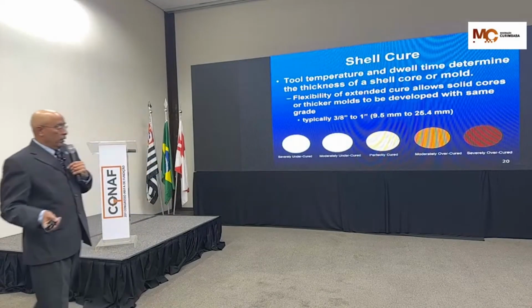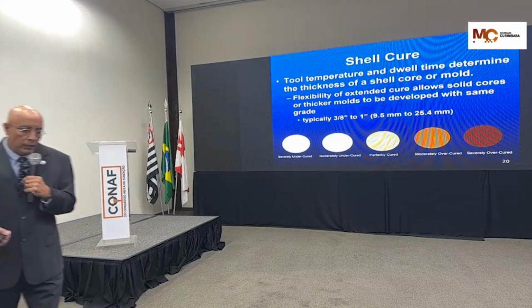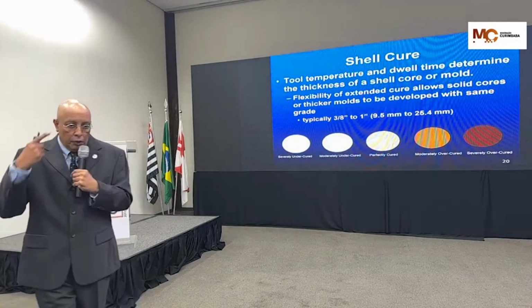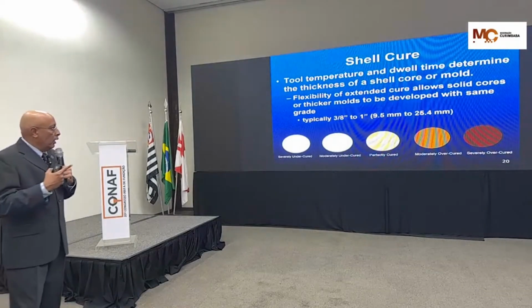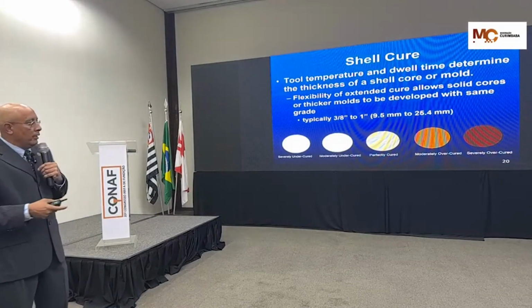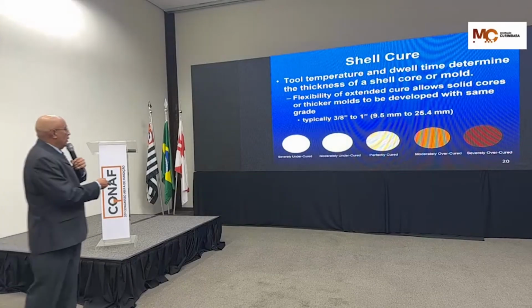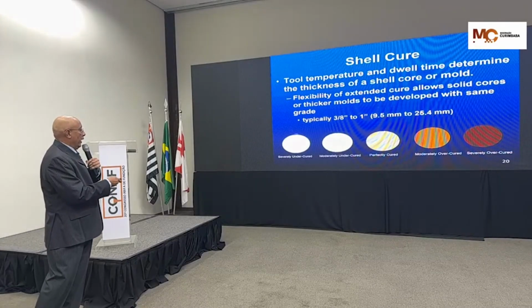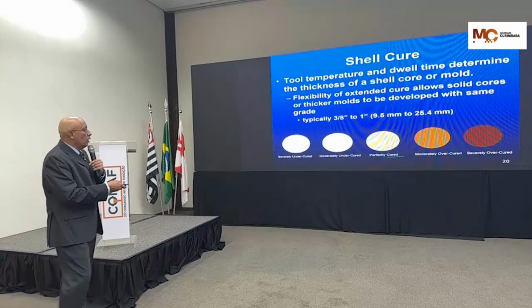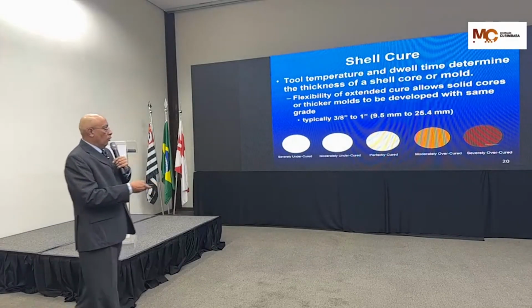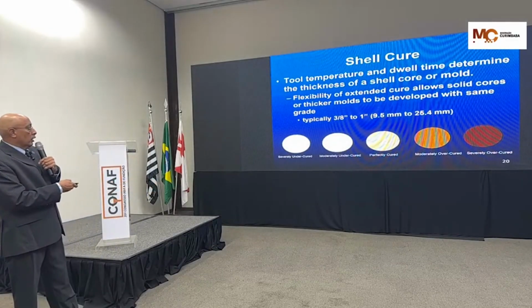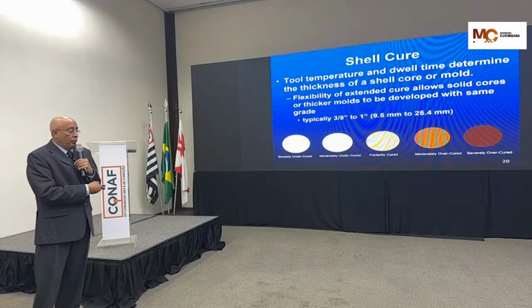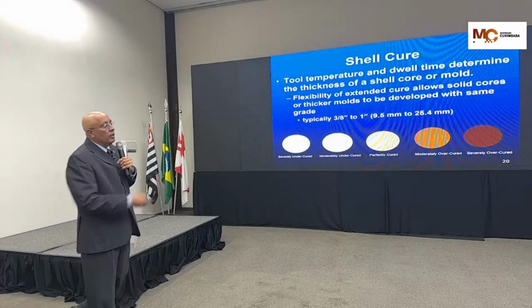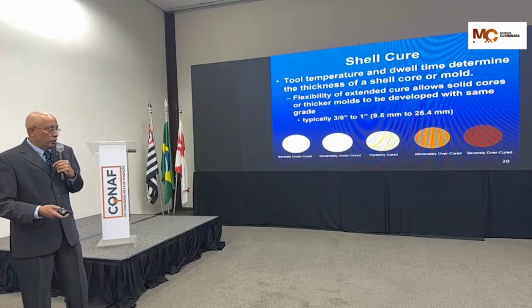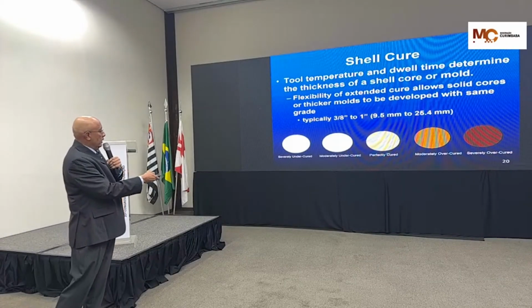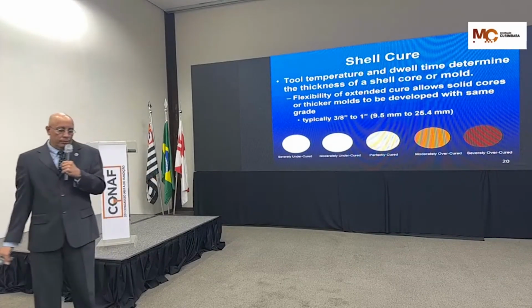Okay. One of the major problems with shell is that it needs visual acuity. We have to use our eyes. And when we cure the shell sand, this depiction is saying my cookie is severely undercured. This cookie is severely overcured. Maybe the undercured cookie may lead to gas-related problems. The overcured cookie has a friable issue, and this khaki tan color is perfectly cured.